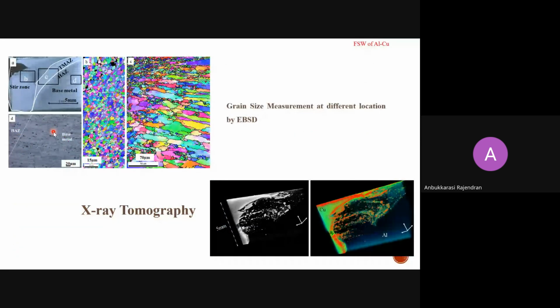This is another weld sample, made by friction stir welding, copper and aluminium. You know that multiple zones develop during friction stir processing or welding. How the grain size varies zone wise, we can study using EBSD analysis.